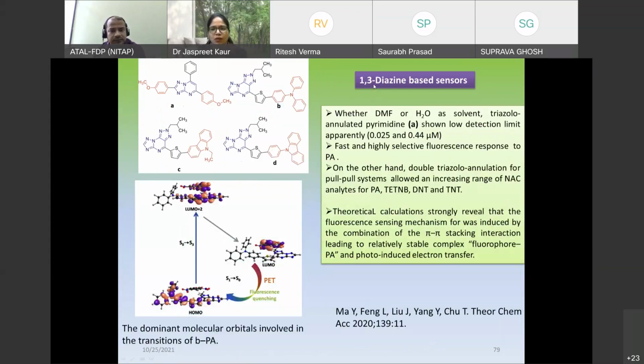Next is the 1,3-diazine based sensors. So here we have a diazine, the core is 1,3-diazine, and there is also a triazole derivative annulated pyrimidine. They also show very good detection limits, 0.025 to 0.44 micromolar. In DMF it is 0.025 micromolar, whereas in water it was 0.44 micromolar, for the detection of picric acid. So again, it is by the PET phenomenon, photoelectron transfer, because of the pi conjugated system.